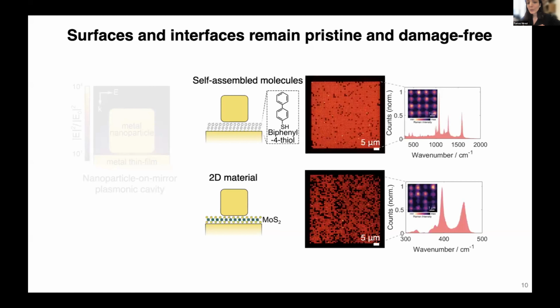So in this case, once we incorporate the materials into devices made through our approach using individual nanoparticle plasmonic cavities and perform enhanced Raman spectroscopy, we see that the Raman signature of the materials is exactly the same as the pristine material, suggesting that there is no additional damage introduced to the material due to the processing technique.